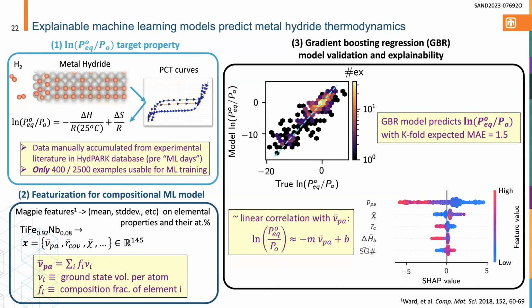What's important is that you have some interpretable insights, especially if you're using something like gradient boosting trees or random forests. There's no reason you shouldn't apply post-analysis methods like SHAP, which tell you how the model outputs depend on the input features. The SHAP value on the x-axis is the contribution of a feature to the model output, and each point is an individual training example in the data set. For v̄pa, you can see that if I have a high value of v̄pa, I have a low value of the equilibrium plateau pressure. Basically it's a log-linear correlation with v̄pa, and then there are other secondary features that tweak the prediction from there.